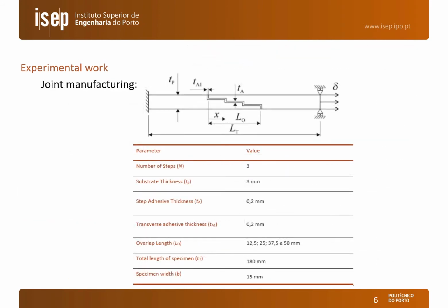We can see in the figure the geometry of the step-lapped joints. We are using a three-step configuration. With this geometry, the adherends are in line with each other, so there is no eccentricity, and we can see the main dimensions of the joints with emphasis on the overlap length, which was the varied parameter in this analysis, with values between 12.5 and 50 millimeters.